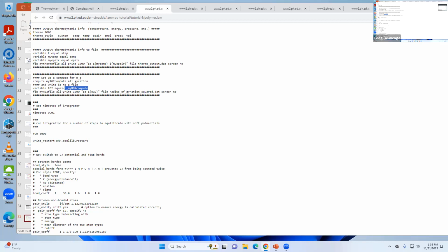So you can know if it's reached equilibrium, because the radius of gyration reaches a fixed value. That's another way, like you can plot the temperature and pressure and see if they settle down. But if this Rg hasn't reached the expected value, Rg squared should be N l squared, number of units times the step length squared, then there's a problem. It has to reach the known value of Rg to reach equilibrium.